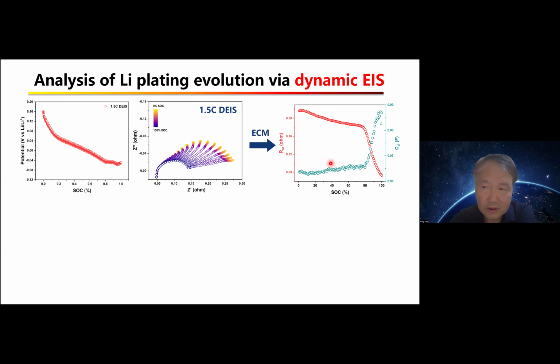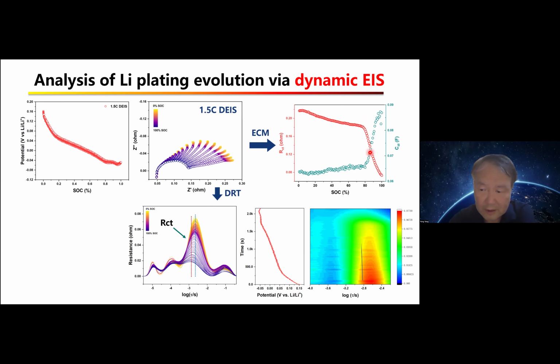You can see using what we call dynamic EIS, during this charging process, if we use some equivalent circuit model, we can see that when the potential is below graphite potential, below 0.0 volts, the charge transfer of the electrode decreases sharply, but also the double layer of the electrode increases sharply. And if we use DRT techniques, we can follow these different reaction times during the charging process.